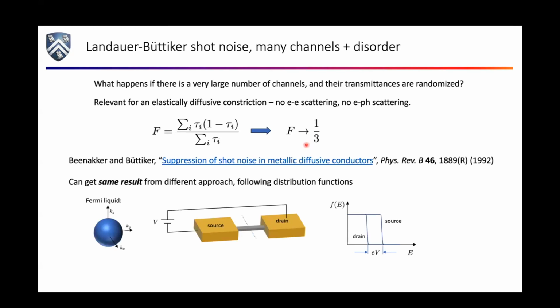There's another way to think about this. Actually, you can do this from the point of view of distribution functions. So my distribution function in my source electrode is going to be a Fermi-Dirac thing. My distribution function in my drain is going to also be a Fermi-Dirac thing, and they're going to be shifted relative to each other by some applied bias, right? If I cut the wire in the middle and I look in the middle, the distribution function for the electrons in the middle is going to be some linear combination of these things. It's going to have a two-step feature. And if you go through and you do the Boltzmann equation, you calculate current correlations, blah, blah, blah, you get that the Fano factor is 1/3, right? So this is what you expect if the electrons don't trade energy with each other, but they just diffuse around like pinballs in some disordered environment.